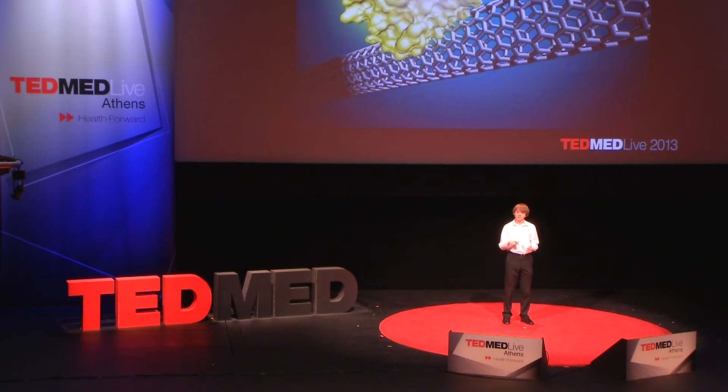However, there's a catch: these networks of carbon nanotubes are extremely flimsy, and since they're so delicate, they need to be supported. That's why I chose to use paper. Making a paper sensor for pancreatic cancer is as simple as making chocolate chip cookies, which I love. Essentially, you start with some water, pour in the nanotubes, add some antibodies, mix it up, then take some paper, dip it, dry it, and you can detect cancer.